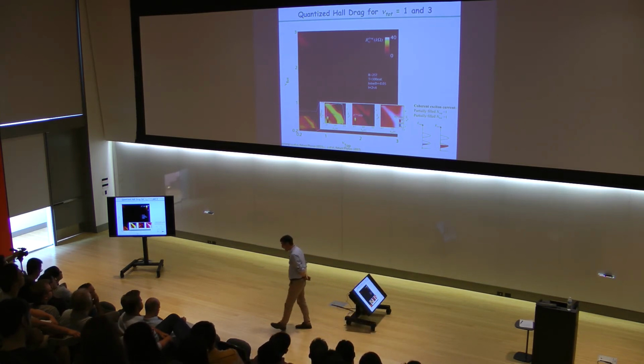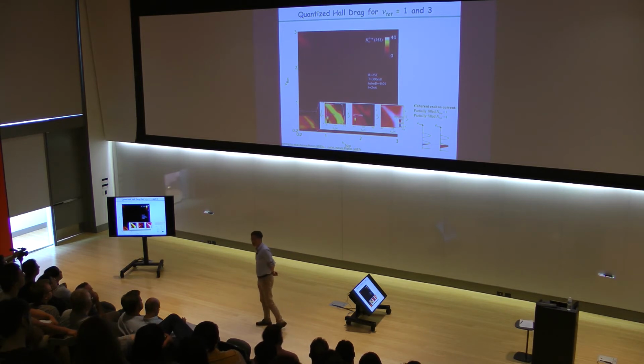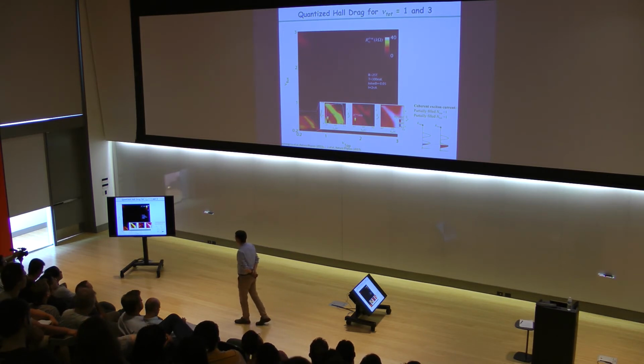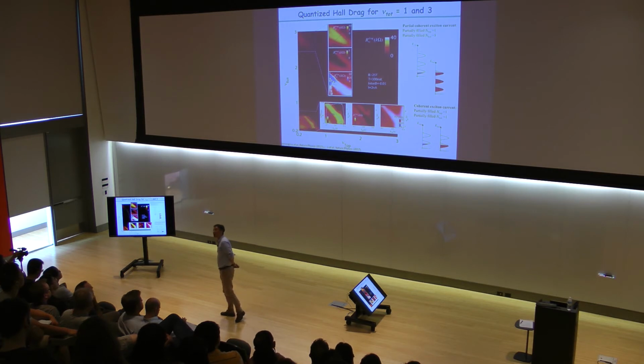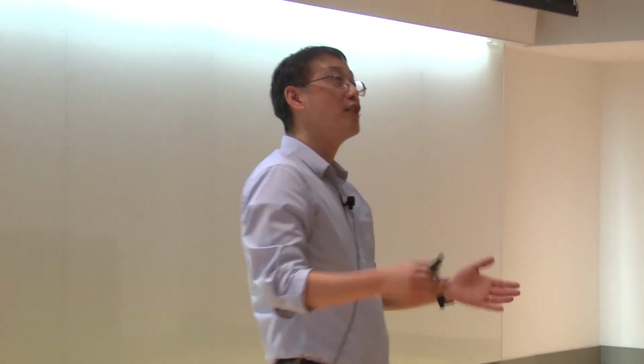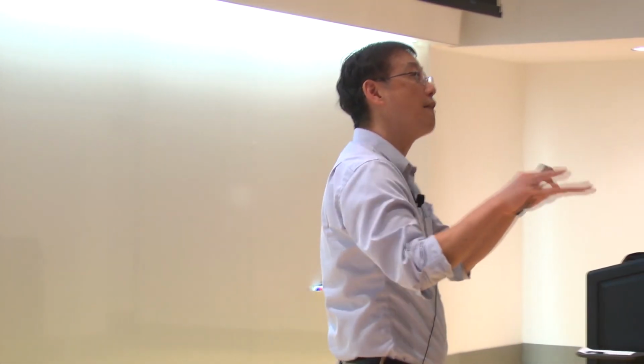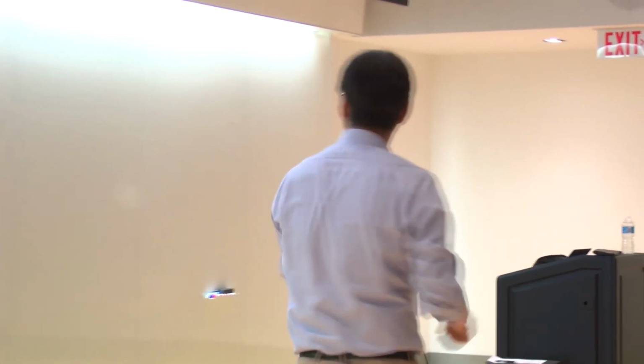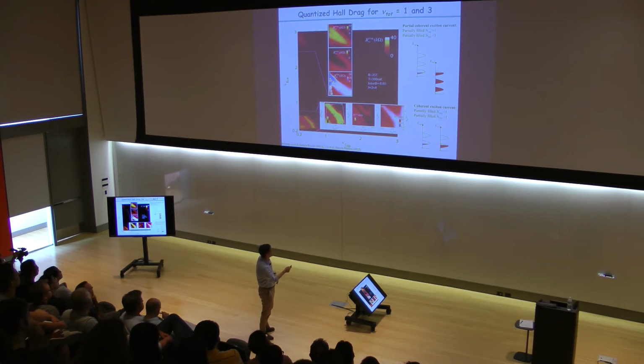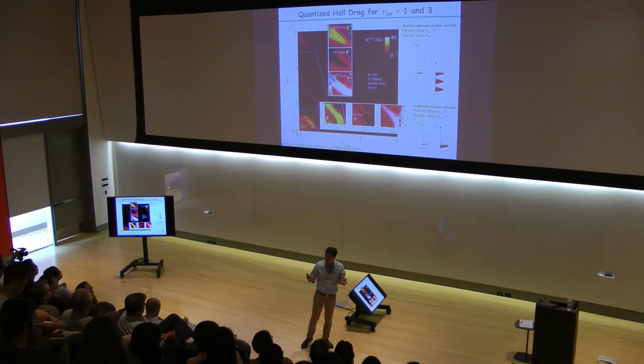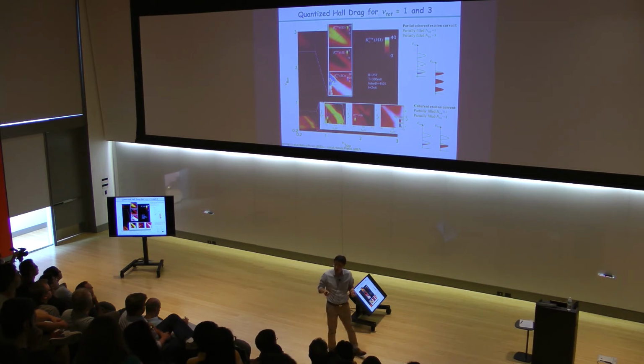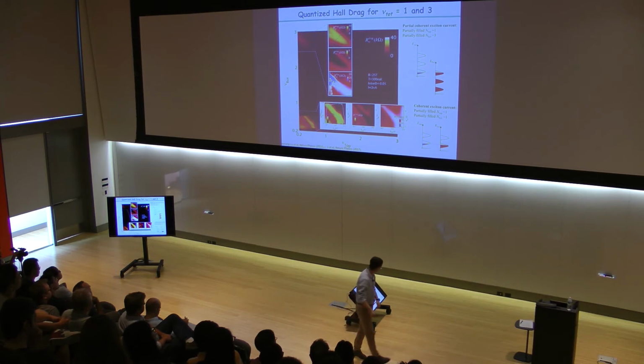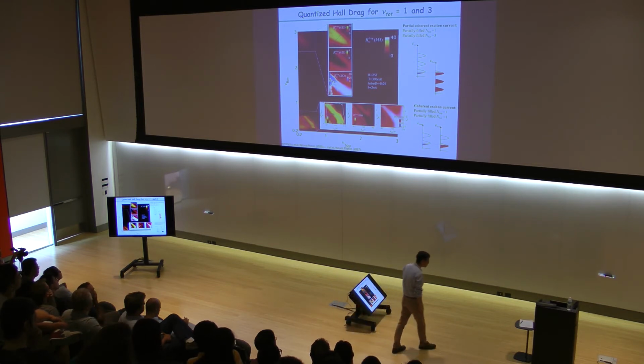So two partially filled Landau levels show a drag quantization, indicating indeed that we are seeing the condensed magneto-exciton in the system, right? On top of that, since we have more capability for tuning the density, the gallium arsenide people did see this in the half-filled Landau level, but in this case, we see those effects in many different Landau levels. For example, from the 2.5-filled Landau level to the half-filled Landau level. We do see again a very similar drag effect, showing that we can also create the exciton condensation in various places of the different Landau levels.